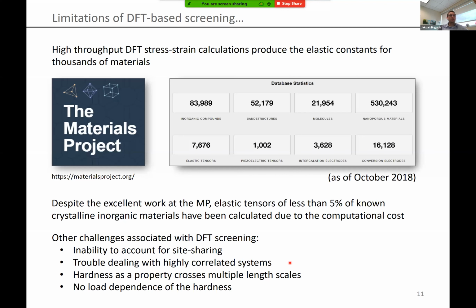Now, because we're also interested in hardness, there are some things that are not even addressable with DFT. Hardness crosses multiple length scales. The idea of using DFT would be amazing, but the fact that we have to not only look at local chemical interactions, but also interactions between different grain structures is going to be a huge challenge. And then finally, there's no ability that I'm aware of to calculate a load dependence of hardness using DFT.